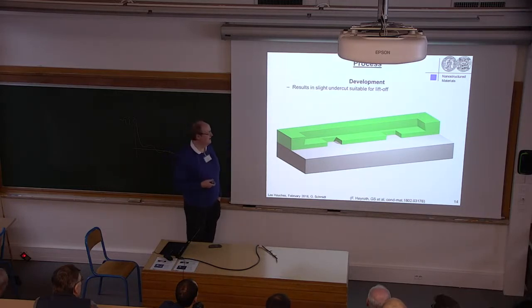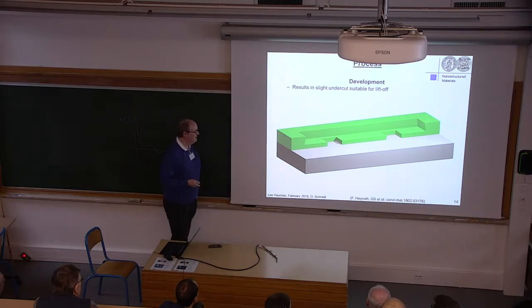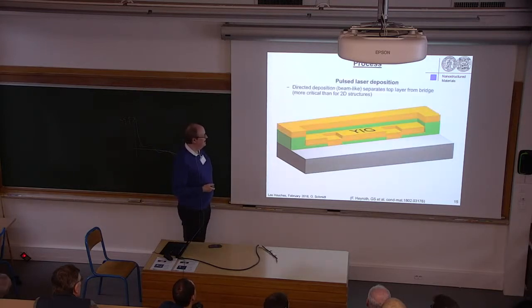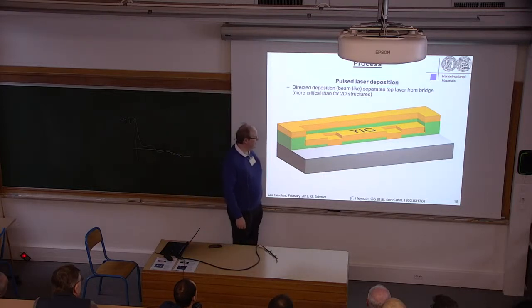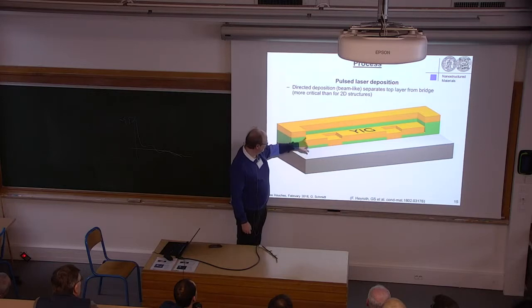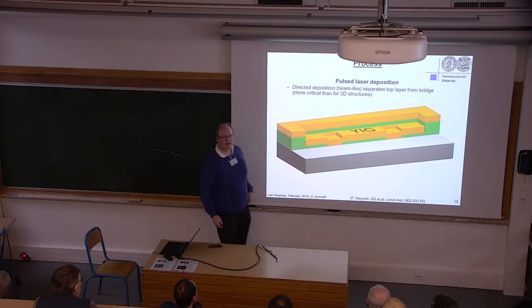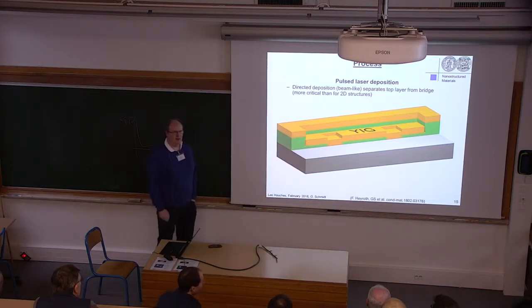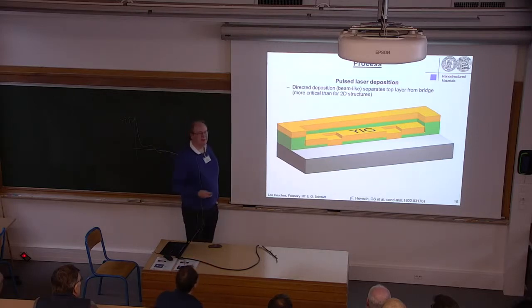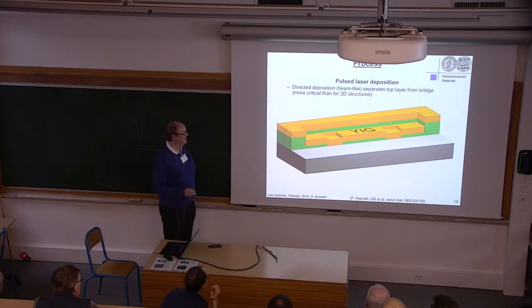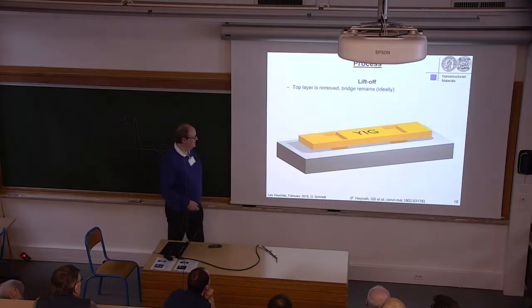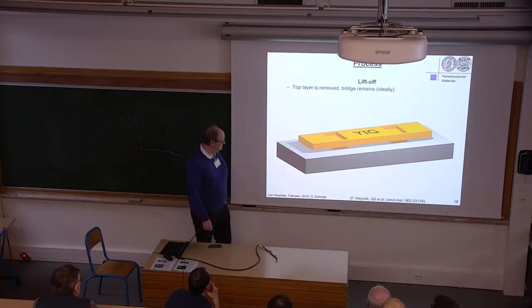So this is the structure after development, and now normally you would evaporate metal and you can make your bridge. In our case, we use PLD and we make YIG. And you can already guess the shape, and you can see here this undercut is actually what allows us to do the liftoff in the end. Finally, you will also see that the result is not as perfect as it looks here, but still it's good enough for us. And now you just have to dissolve the PMMA, and then the top just floats away. And this remains.